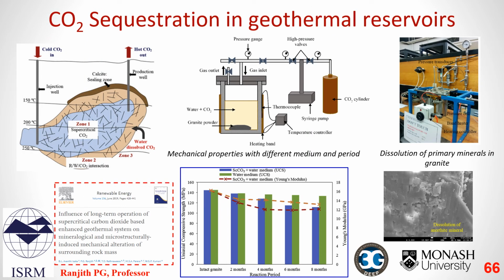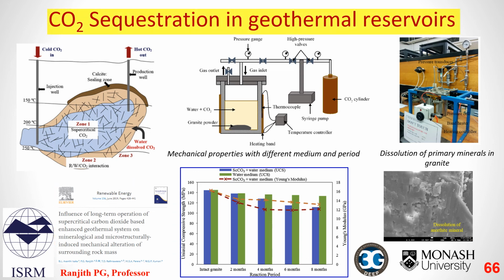As can be seen from our paper published in Renewable Energy Journal, we utilized these custom-made high-temperature, high-pressure reactors to perform long-term geochemical tests for different reservoir conditions. Here you can see some experimental results targeting CO2 sequestration in geothermal reservoirs. We found that microstructural and mineralogical alterations weaken the mechanical properties of the specimen with time. We also identified possible precipitation of clay minerals during the long-term reactions. This emphasizes CO2 sequestration possibility during long-term operation in CO2-based geothermal reservoirs.